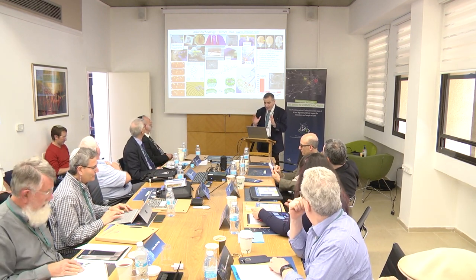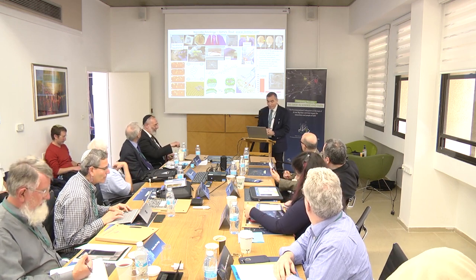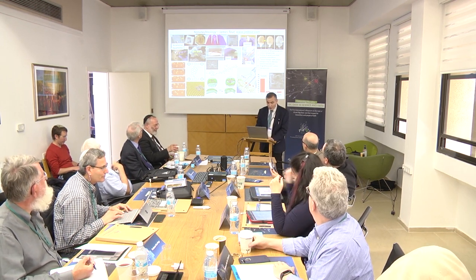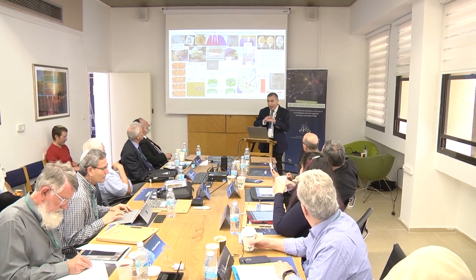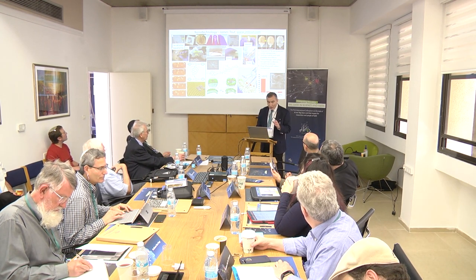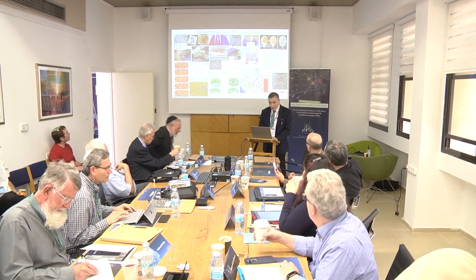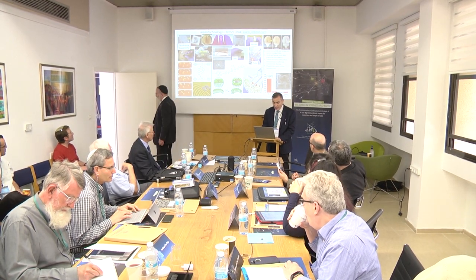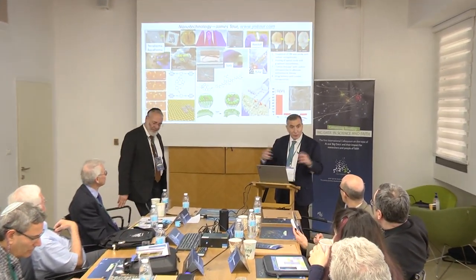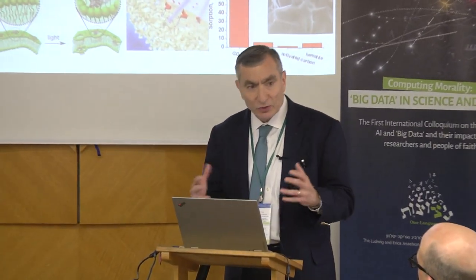This is a busy slide, and I'm going to spend a lot of time on this to give you an overview of the work that we're working on. This is a topic called laser-induced graphene. Most graphene — graphene is single-atom-thick sheets of graphite — is grown at 1,000 degrees on a copper substrate. We found a way to grow it at room temperature in the air using lasers. It's a whole new area called laser-induced graphene. We first found this in 2014, and we've published about a dozen papers. Now there's about a paper a week coming out from around the world. It's really taking off, and it'll probably be the first way that graphene is really commercialized.